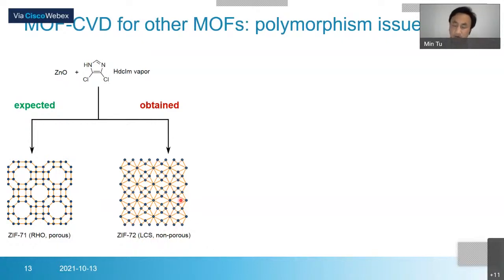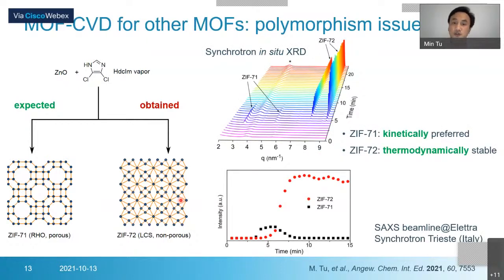So we asked ourselves what the reason behind this is. Why, for ZIF-8, can we get the porous structure, but for this kind of linker we cannot, and instead get the dense structure? We went to the synchrotron to do in situ XRD measurements, to monitor the reaction of zinc oxide and dichloroimidazole. At the very beginning we can see the formation of ZIF-71, with these reflections belonging to ZIF-71. This is the porous structure. But with the reaction, we see the disappearance of ZIF-71 and the formation of the other MOF, ZIF-72, the dense structure.